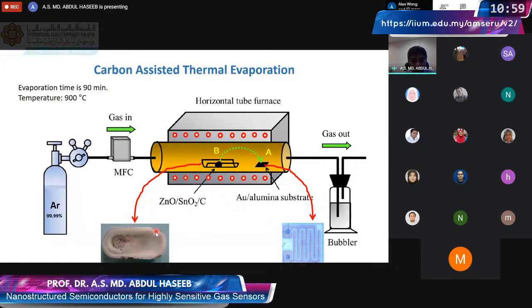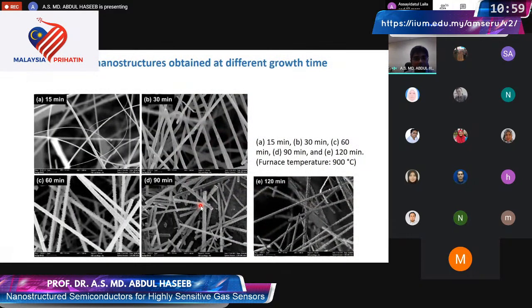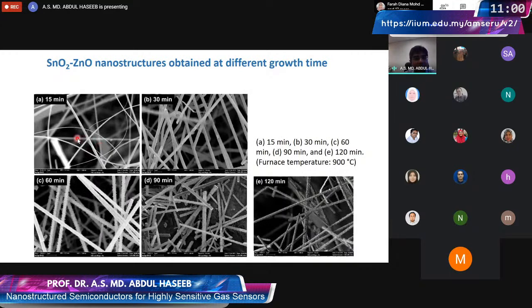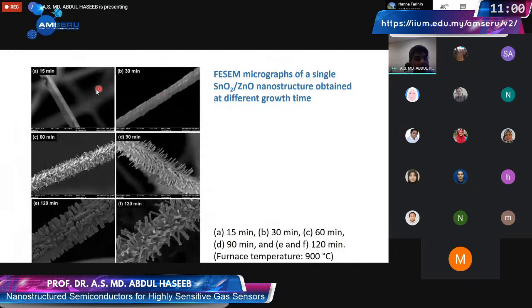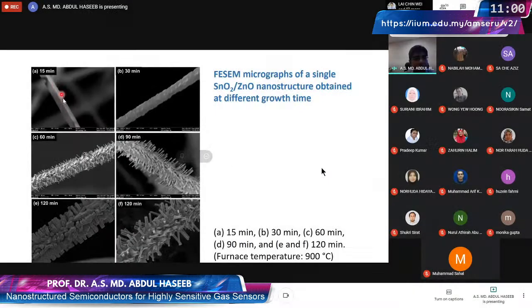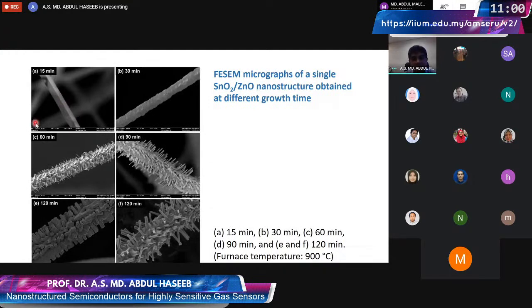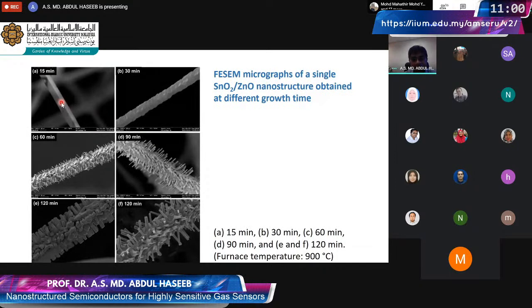I will show you some interesting morphology of the nanowires that grow at these two places. First, let us look at the nanowire that grows on the boat. So these are the pictures. If you look at the variation of the nanostructures that form, it changes with time. At the beginning, they are very thin and smooth, round and rectangular in shape. As time goes on, they become more rough at this low magnification. But if you look at high magnification, things become very clear. In the initial 15 minutes, the material that grows on the boat wall is rectangular. We will show later on that this is actually tin oxide that grows. And then, sorry, it's zinc oxide. I'll show you later on.